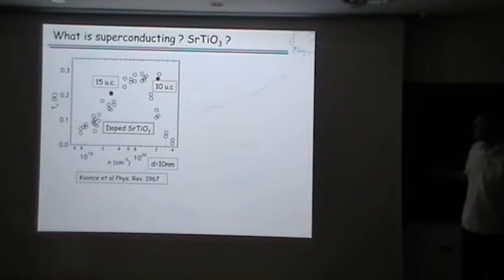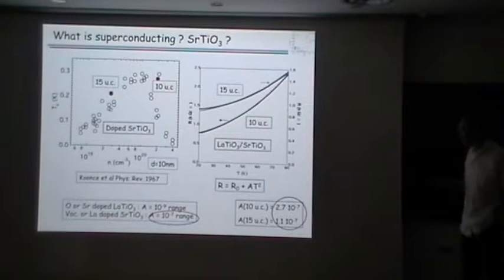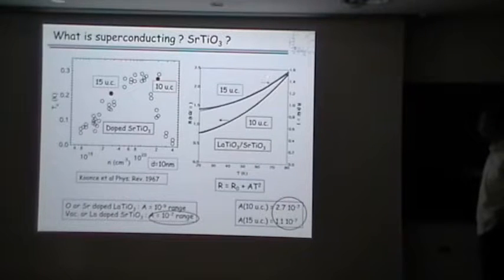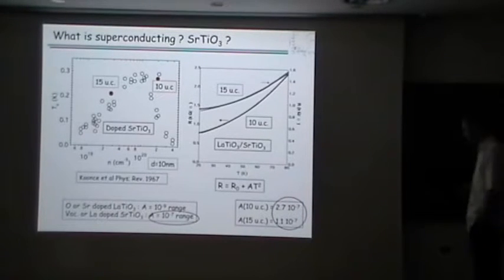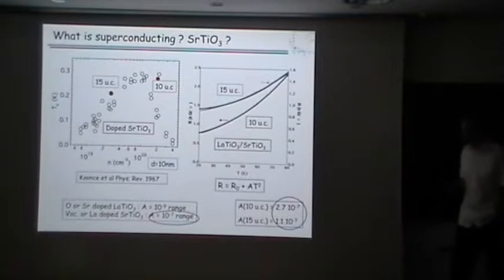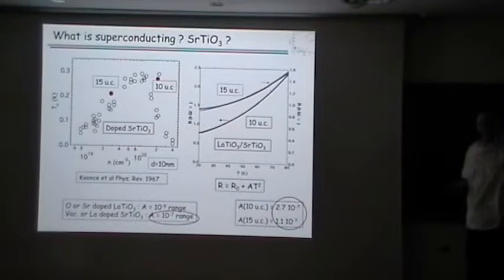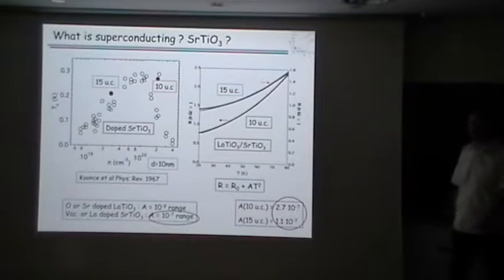Okay, so what we have found here is that in fact those systems are very Fermi-like. They have a Fermi-like behavior. Of course, you wonder what are the electrons? Are they in the lanthanum titanate? Are they in the strontium titanate? I explained to you based on the calculation that probably there are more in the strontium titanate system. If you analyze, for instance, the A coefficient of this temperature dependence, it's more close to doped strontium titanate than to doped lanthanum titanate. Okay, so probably the electrons are more in the strontium titanate.